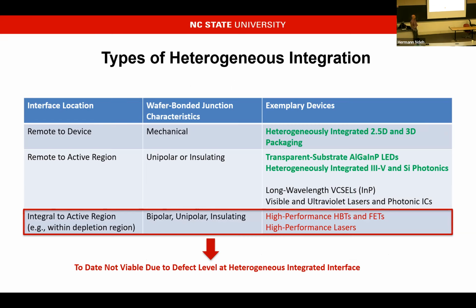Additional things that we're working on is pushing the heterogeneous integration envelope further. There are different places you can put the interface. You can wafer bond where the interface is remote to the device, and that's what people do in 2.5D and 3D packaging. You can make it remote to the active region, and that's really what we did in transparent substrate LEDs. It's what people do in heterogeneously integrated silicon photonics. But what you'd really like to do is make that interface integral to the active region, meaning within the depletion region. And if you do that, you really could make very different kinds of HBT, FET, and laser structures.